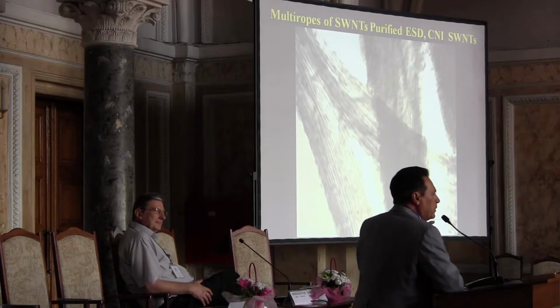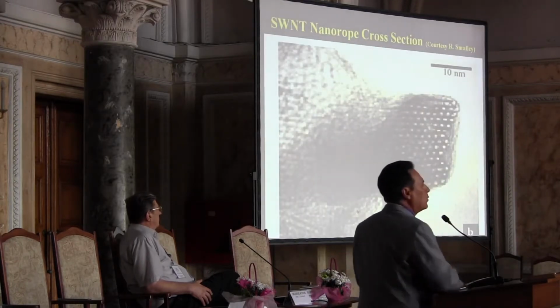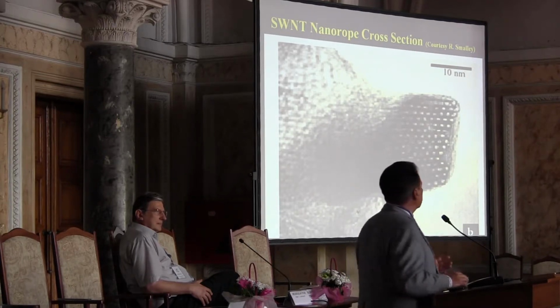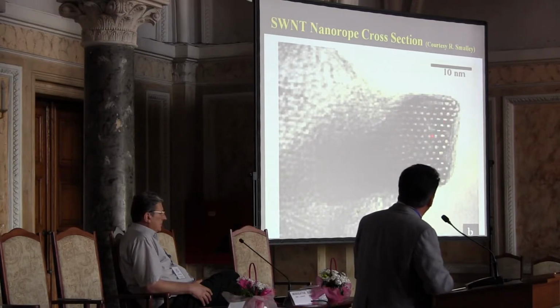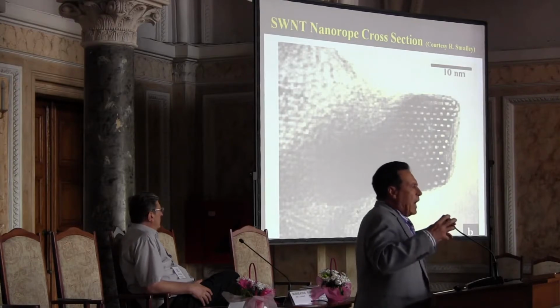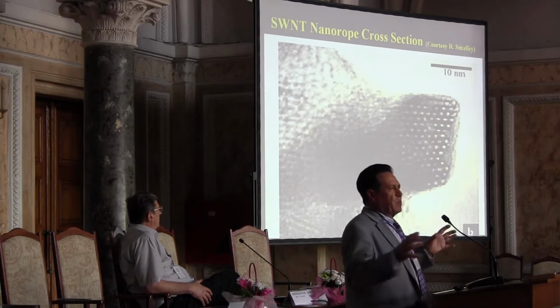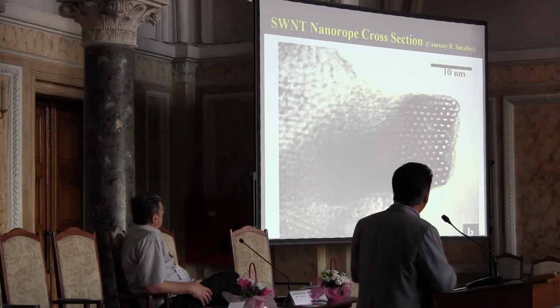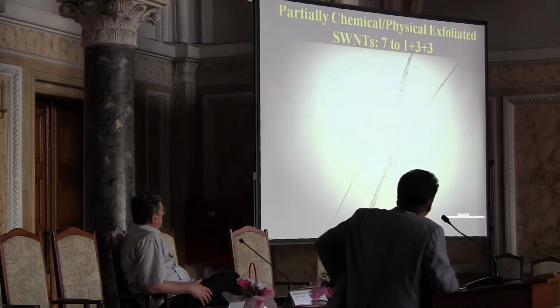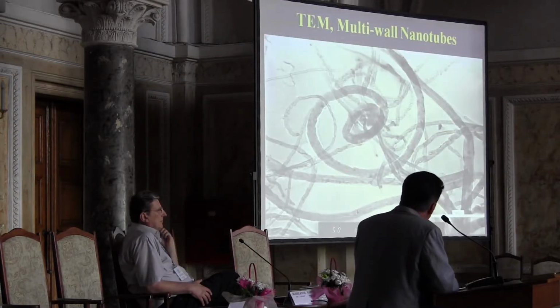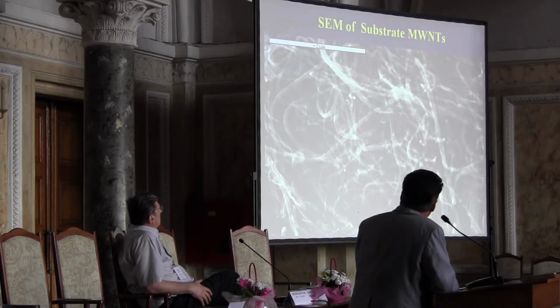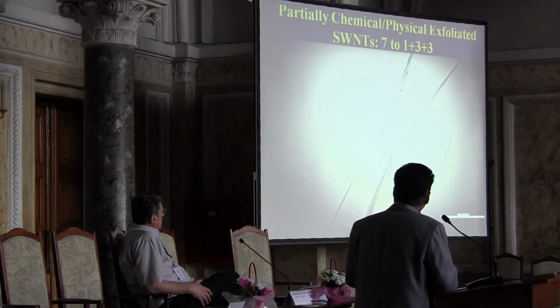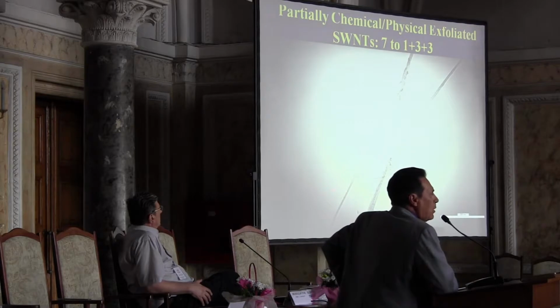You cannot build any multifunctional material using units of this type. These materials need to be exfoliated and functionalized. What you are seeing here is a cross section of one of these ropes. These carbon nanotubes really want to stay together, and if you succeed in separating them, they would like to be together again. What you are seeing here is actually the chemical and physical exfoliation. There are various processes, and typically what you have here is a unit. This is a single wall nanotube, typically with a diameter of 1 nanometer. These are the units that we would like to work with.